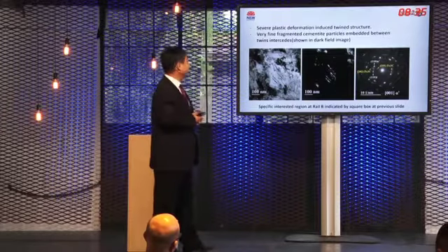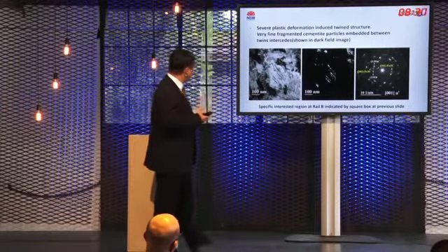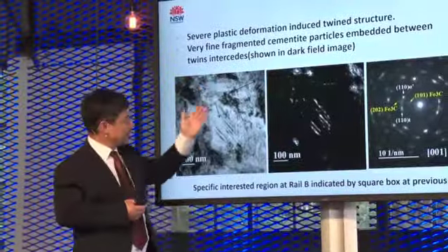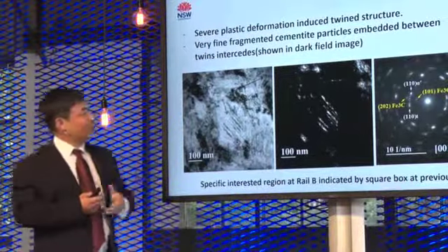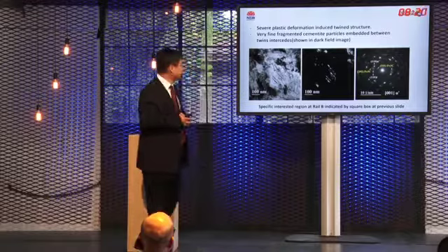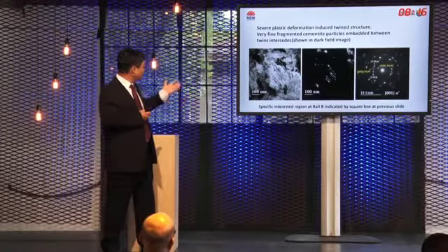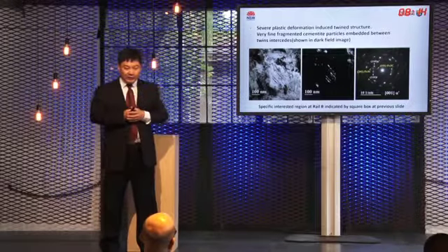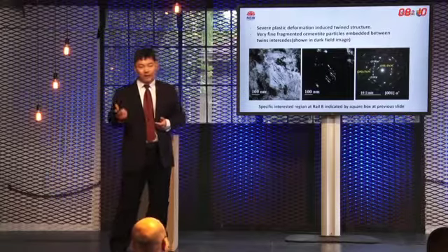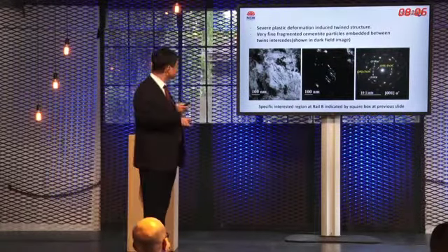Here, it shows what truly happened for the stable traffic region. You clearly show the twinning structures. This twinning is caused by the severe plastic deformation. So actually, so far, we find different traffic conditions. High braking, stable traffic, you generate different white etching layers.